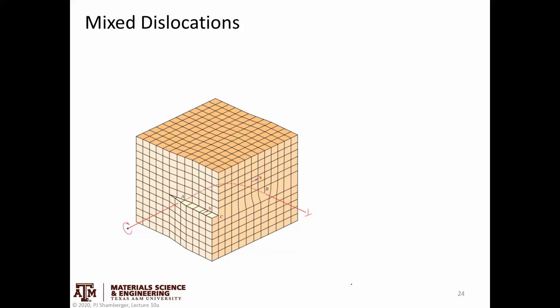The Burgers vector is conserved, but the direction of the dislocation line itself can be bent. If the dislocation vector starts off pointing one way and then bends in the material, that's totally okay. While the dislocation changes direction — on one surface you see a screw dislocation and on the right-hand face you see an edge dislocation — the Burgers vector is pointing in the same exact direction with the same magnitude. For a particular dislocation, the Burgers vector is constant all the way along that dislocation line. It cannot change unless that dislocation has interacted with other dislocations or with the edge of the crystal.